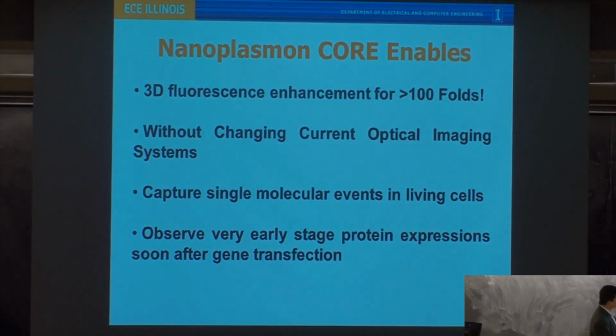The Nanoplasmon core, we want to enable three-dimensional, not just two-dimensional, because most of the cells, especially when you do a large population of cell culture, you have three-dimensional spheroidal structures. So we wanted to give not only just on surface, but three-dimensional fluorescent enhancement for more than 100 folds. Okay. And if before you can detect 100 molecules using the system, then using our nanoengineering surface, possibly you can detect just one molecule. So this is the concept right here. And without changing any current optical imaging systems.